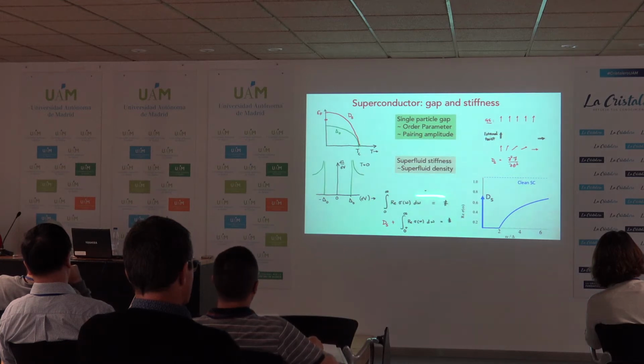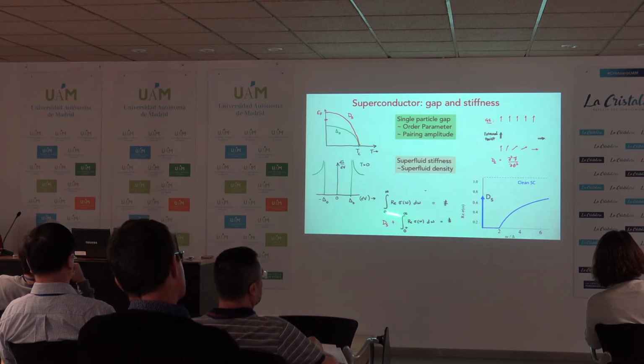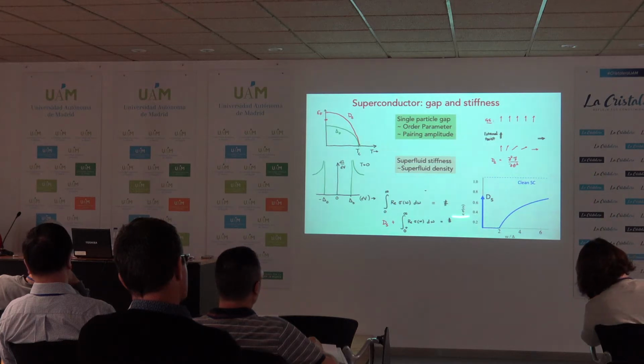And this is the absorption at finite frequencies. But in addition, there is an accelerating part of the condensate which appears at zero frequency, which is this added weight. So in the experiment, you really measure this part of the absorption. You know the right-hand side, and from the difference, you can get the superfluid stiffness. So this is the way you can get the two important properties of the superconductor, the gap and the stiffness.